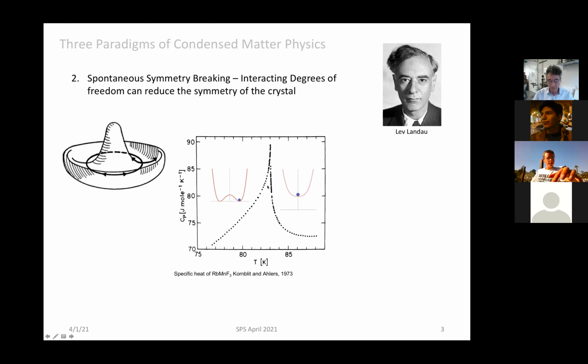And one of the nice properties that I do a lot of measurements of is the specific heat. If you put energy into a sample, you'll make its temperature rise, and the specific heat is the ratio of those two. It's also the first derivative of the internal energy with respect to temperature. So at the temperature where the symmetry is broken, you tend to get anomalies in the thermodynamic quantities. And this shows the specific heat. And this leads to this phenomenon of spontaneous symmetry breaking. The reason it's called spontaneous is that it comes from the interactions. Okay, that's what that means.